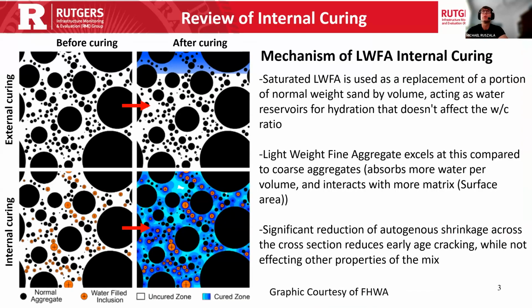So going into what the mechanism of lightweight fine aggregate is, it's effectively a porous sand that's used as a replacement of normal weight sand by volume. It acts as a water reservoir, so it doesn't affect the water cement ratio, but effectively allows more water to be introduced into the mix. As you can see with this diagram from Federal Highway,